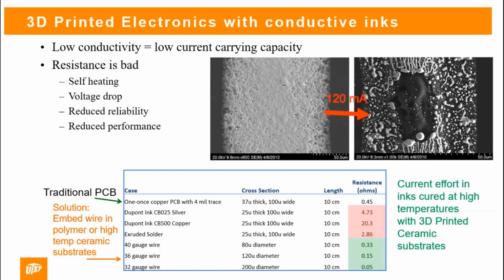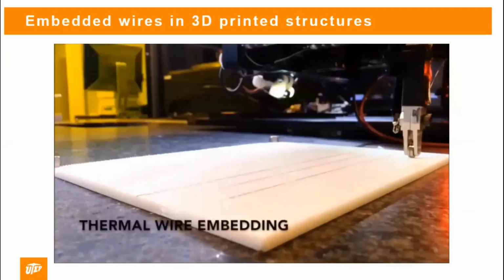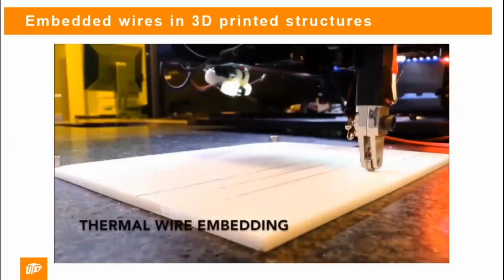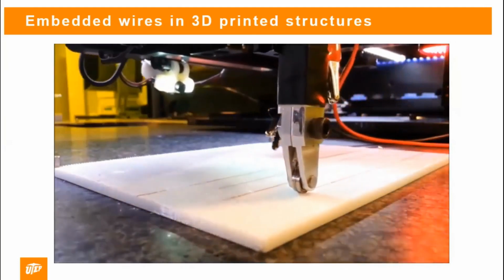And I'll say that since then, that was one solution. The second thing we're looking at, this certainly isn't flexible, but you can 3D print ceramics now, and you could put inks onto those, and then you can fire those at much higher temperatures because the substrate will not limit what you can do. So I'll show that in a little bit. So here's a process. You can see some electrodes.